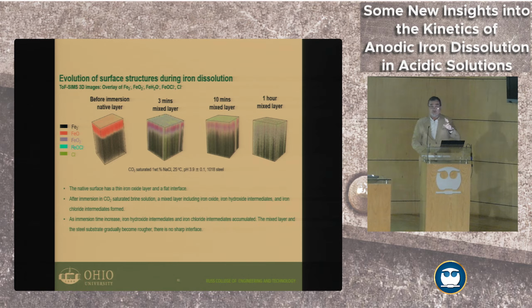So if they have a different composition, you can possibly distinguish them by changing the environment in which they are. Of course, you can change the potential, like you said, and that may also distinguish them, etc., etc. So that's the only way to know if there's more than 2 if they happen at the same time. And some of them show up at high potentials where they don't show up at low potential. In other words, some of these pathways are there, but kind of dormant until you hit a particular potential and suddenly you say, oh, this is good for me now, so now I'm showing up. Like that chloride pathway shows up at the higher potential, the lower potential is kind of not there. It's there, but not doing much.